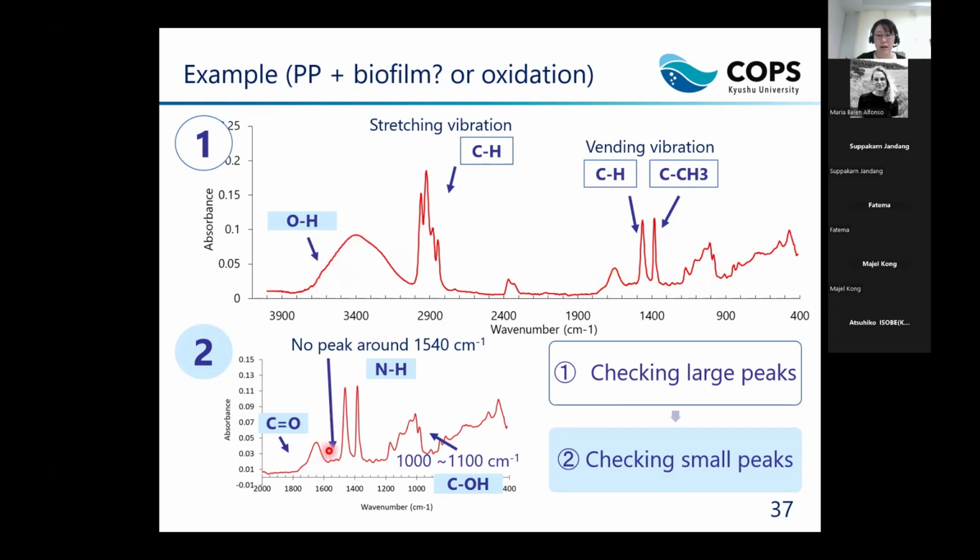And if you compare the data with an infrared spectral frequency table, you can find here is the signal of CO, and here is COH, and here is OH. So you can say this is a kind of degradation, or CO2 signals are there, something like that.